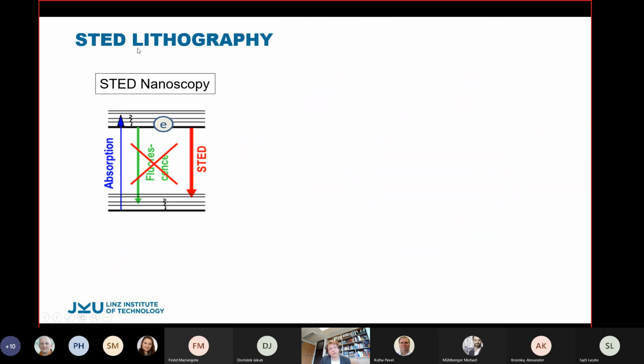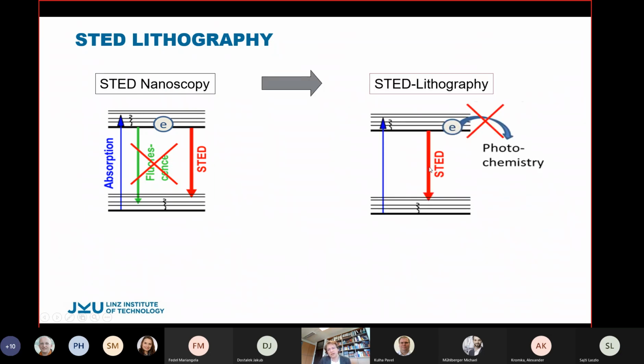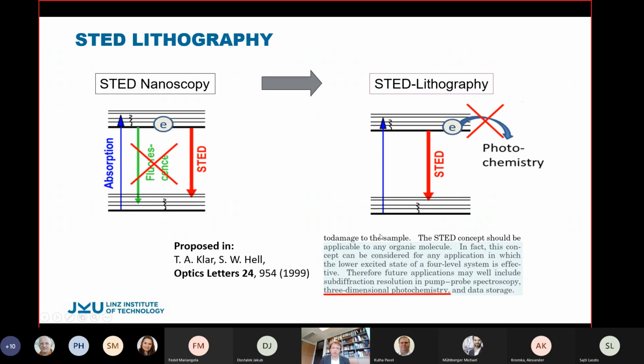And now we have seen that we can use stimulated emission for depletion. That's STED, stimulated emission depletion microscopy or nanoscopy, to improve microscopy. Can we turn it to STED lithography? The idea is we have a starter for the polymerization. So you absorb light, and then the excess energy of the electron is used for photochemistry, for instance, for polymerization. And if we bring down the electron fast enough, we can prevent photochemistry in the outer rim of the point spread function. We proposed that already more than 20 years ago. So the STED concept should be applicable also for 3-dimensional photochemistry.